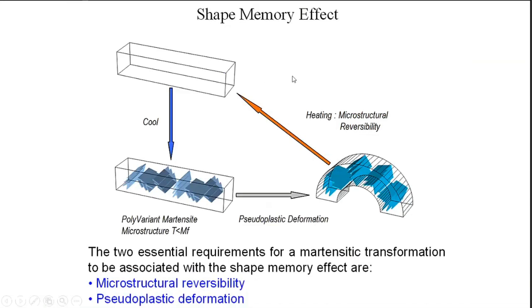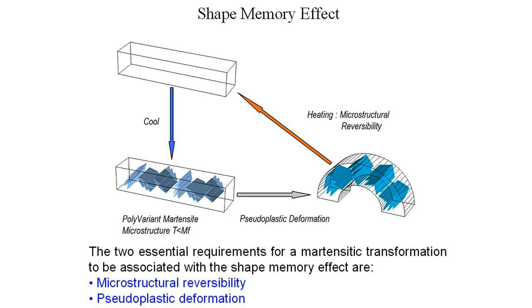So one can ask the question that if there are 24 variants when you cool it, there could be a few crystals as they go back. It needn't be just one. And so that's the important thing, that you also have a choice of orientation of the austenite grain when you heat it. And what this microstructural reversibility assures you is that that will not happen, and all of them will give rise to the original one that you started with. And if you remember that flower, I said it was hot rolled and made into flat strips. So that was the shape in which the austenite was made. And all we did is we cut the flowers, and when we deformed it, that is what we have done here in this case of pseudoplastic deformation.